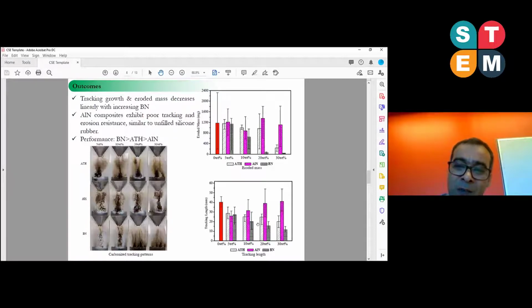The same pattern is observed in the tracking length. We have to physically measure the tracking length. Even with the BN, we have seen very good results, followed by the ATH, and the AlN doesn't perform well, the same as unfilled silicone rubber.